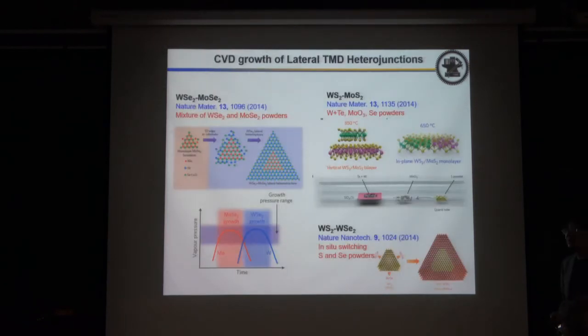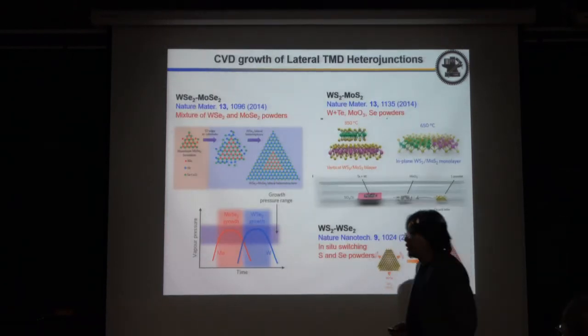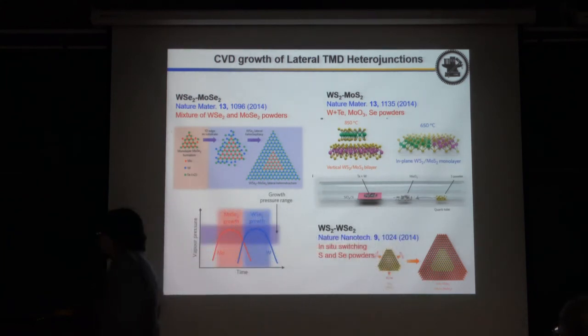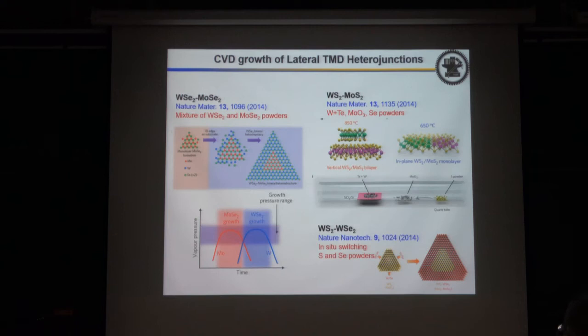Is the platinum selenide contact resistance significantly better than the MoS2 you were showing? In this case, if you increase the thickness, actually yes, because it is semi-metal. The contact resistance can be lower than the typical value now in MoS2, maybe a few hundred kilo-ohm micron, but they can reduce down to below a kilo-ohm micron. Below a kilo-ohm, so this is very promising. And what's the mobility? In monolayer PtSe2, our mobility is now maybe 6 or 10 around this range. Room temperature? Room temperature, yes.